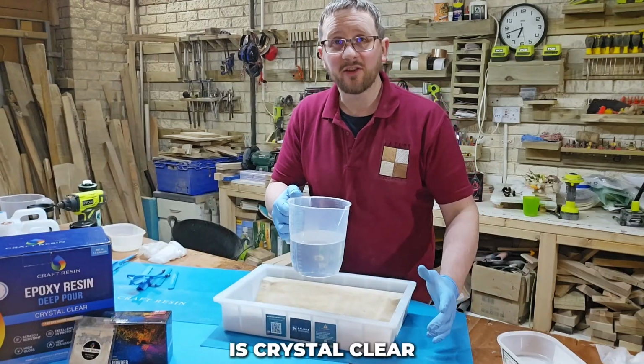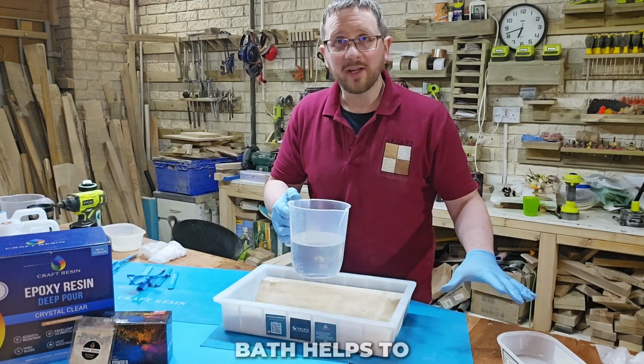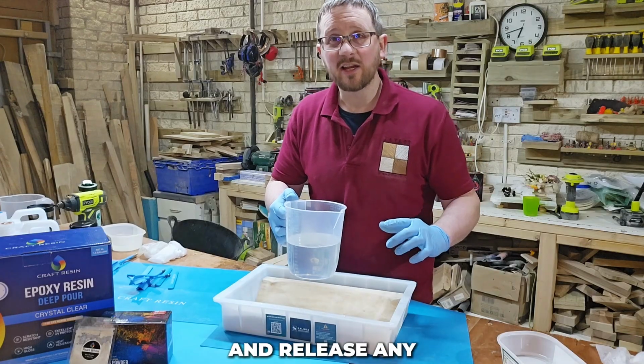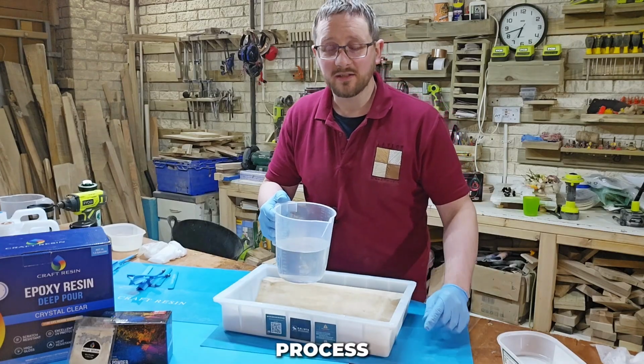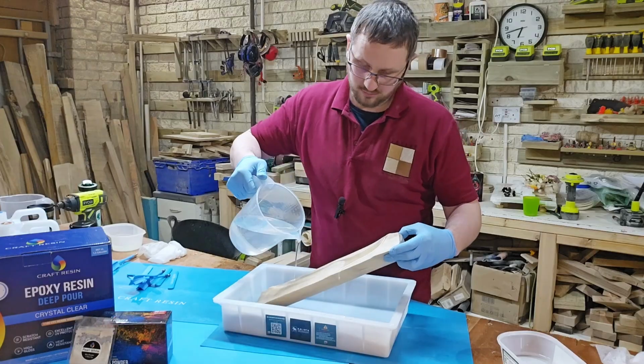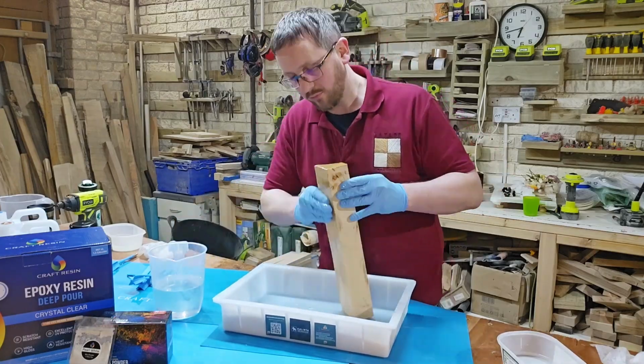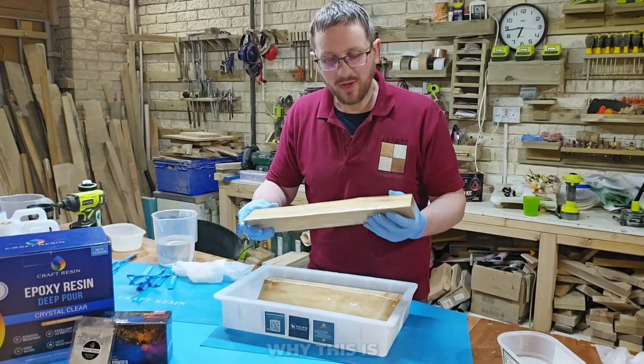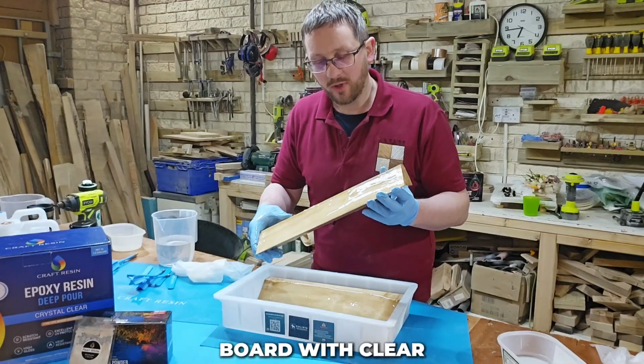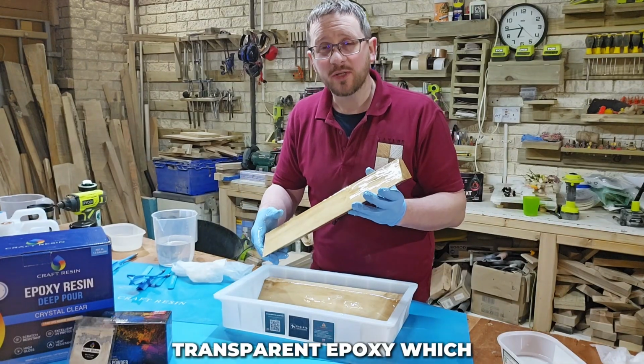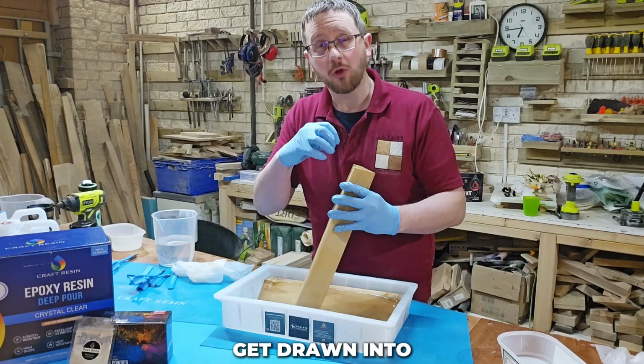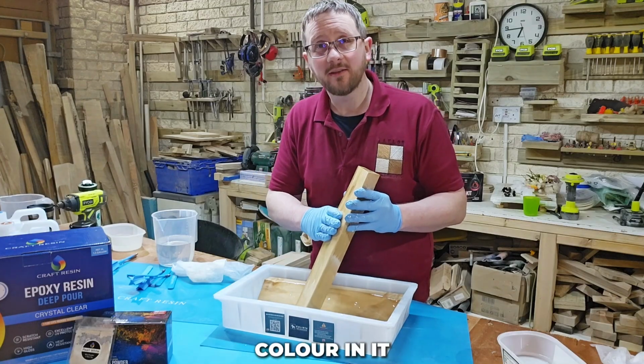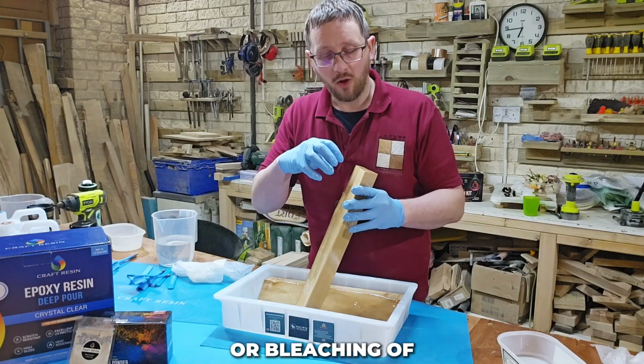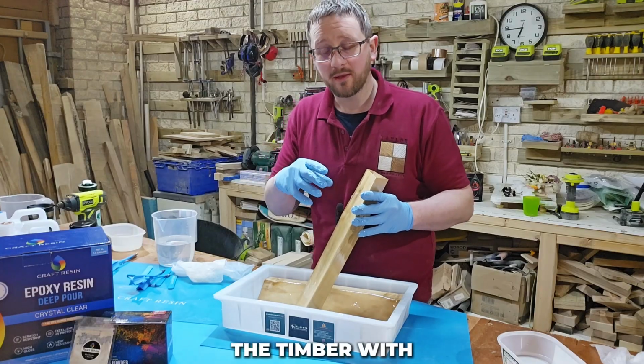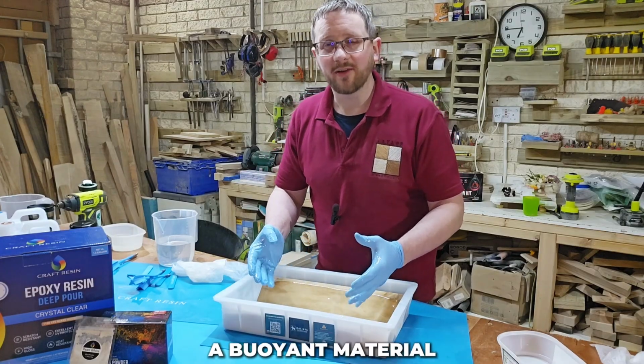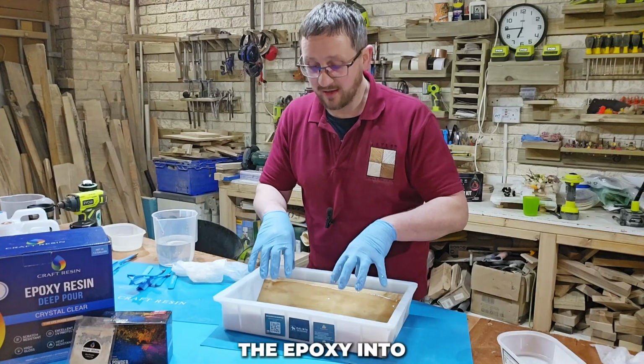And the resin is crystal clear now. All the bubbles are gone. The hot water bath helps raise the temperature and release any bubbles that we introduced during the mixing process. So just to explain why this is important again, we've just went and covered our board with clear transparent epoxy, which means that that clear transparent epoxy will get drawn into the board. As there's no colour in it, it's not going to cause any feathering or bleaching of the timber with the epoxy. As timber is a buoyant material, it will float when we pour the epoxy into the tray.